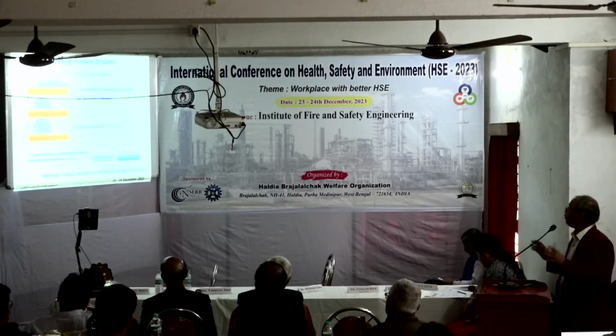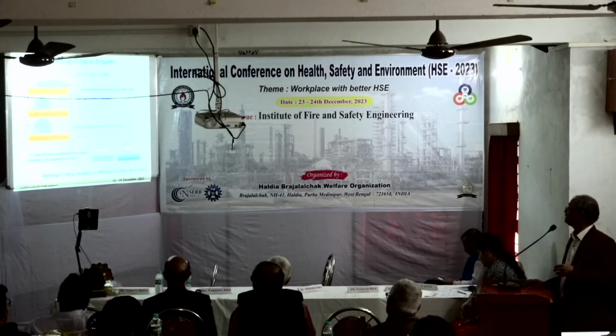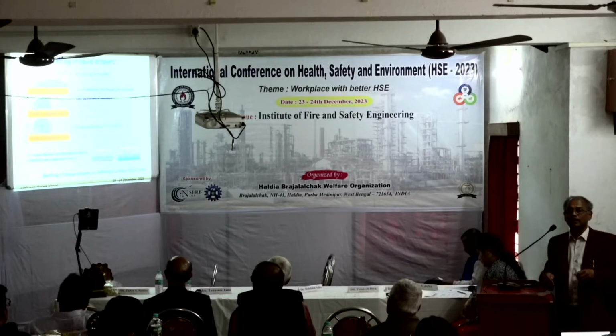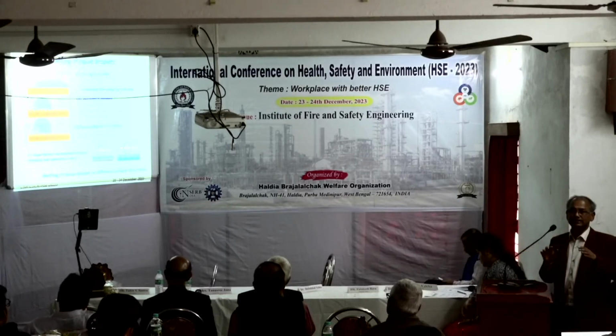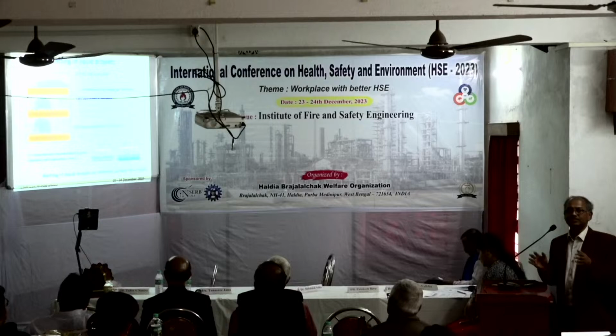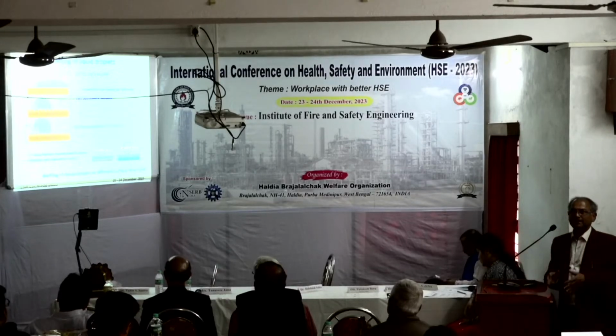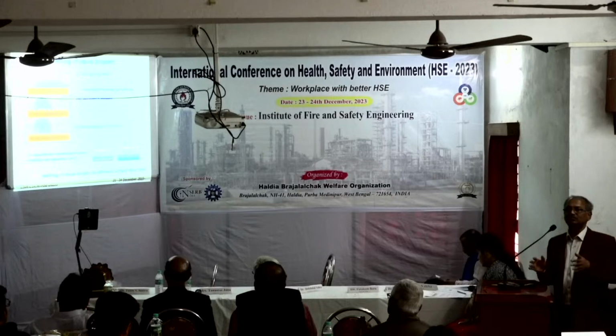Actually, that is governed by various equations, and in this Cassie-Baxter equation, hierarchical surface roughness is very much required to get this property. And combining this hierarchical surface roughness, in the presence of low surface energy material, we can develop a permanent super hydrophobic surface on any substrate.